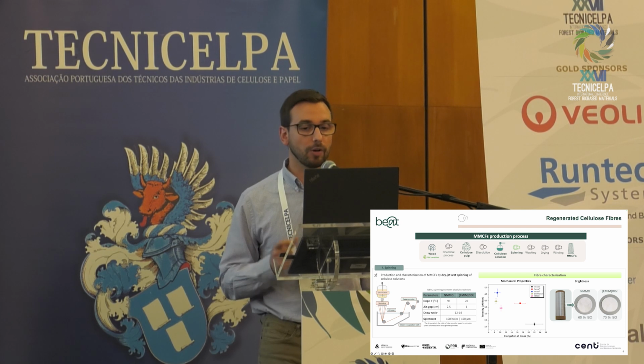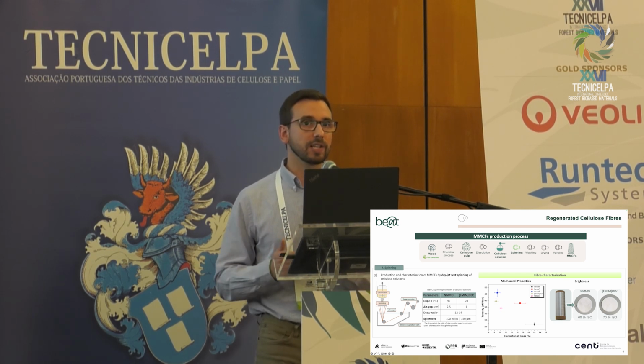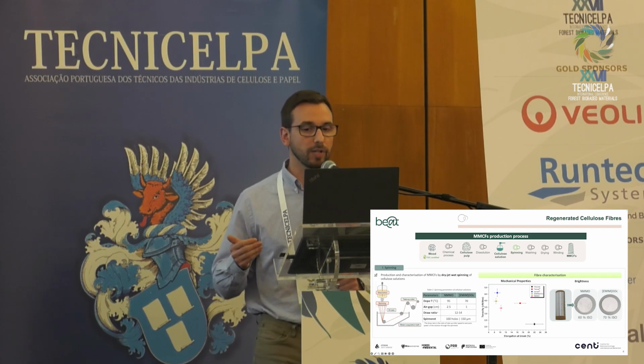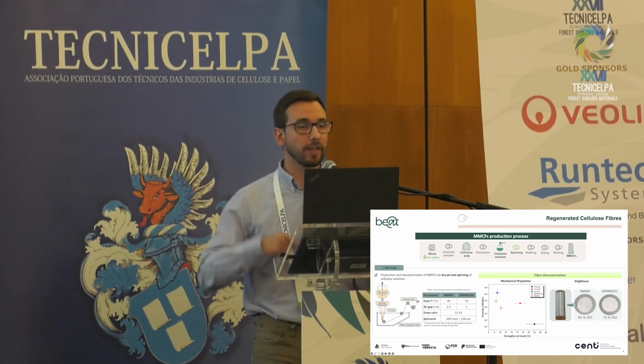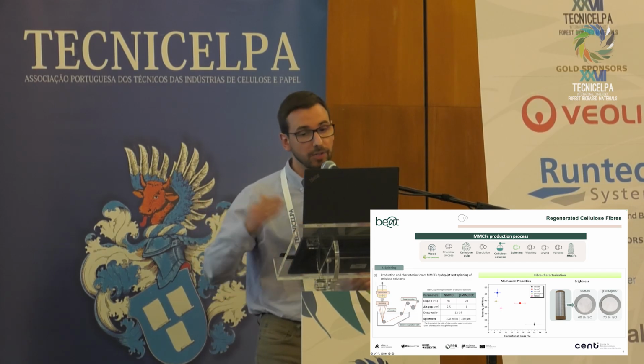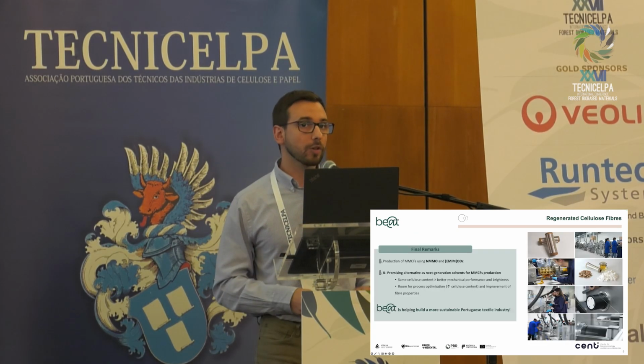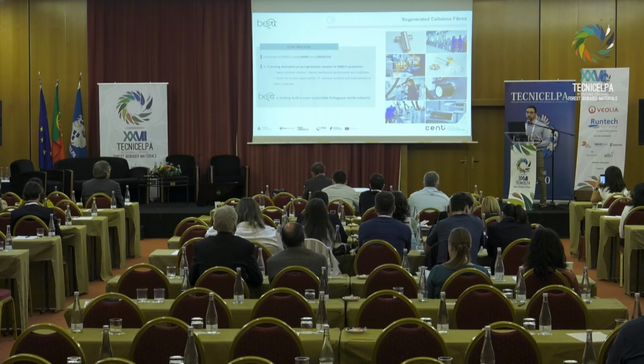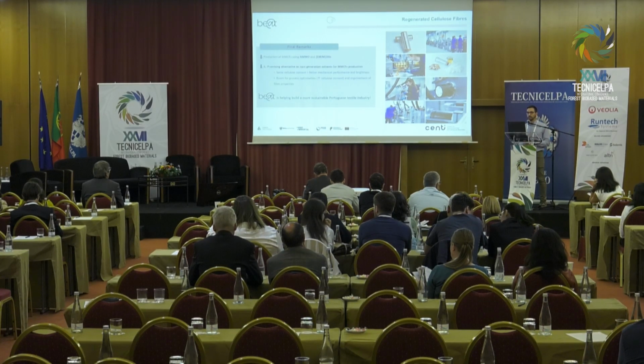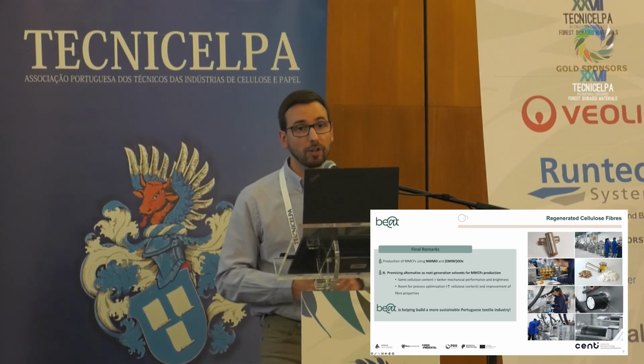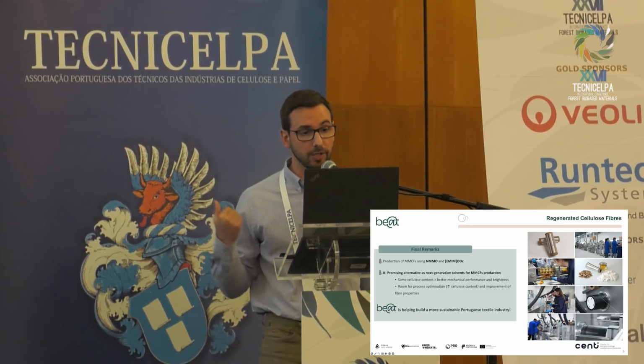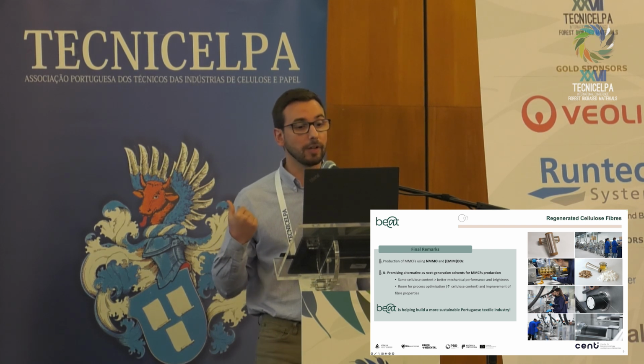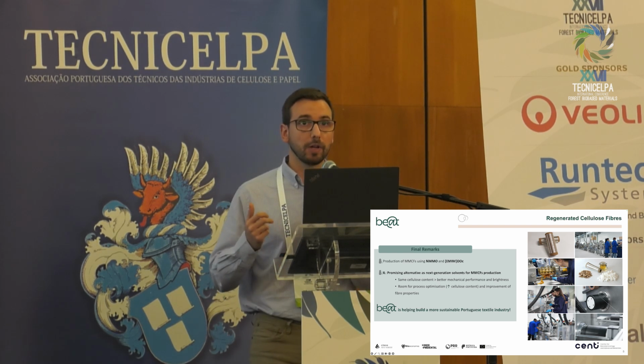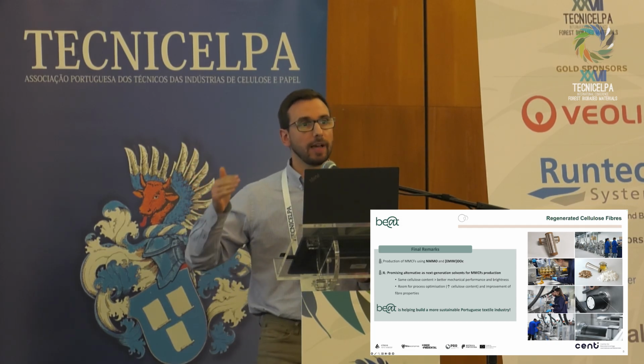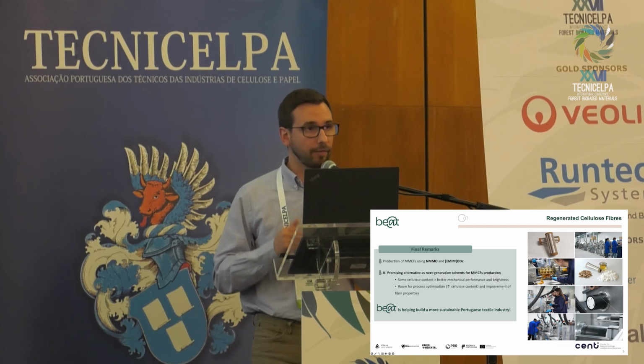Another interesting thing that we saw was that the fibers were substantially brighter when we used the ionic liquid as a solvent. And this is also interesting when you think about energy and chemical consumption in the bleaching of these fibers. So what do we want you to take away from this? Basically, in our opinion, we are talking about very promising alternatives for next generation solvents for cellulose when we talk about ionic liquids in particular, and in this case this one. We see that we were able to reach higher tenacities, higher brightness and effective dissolution.